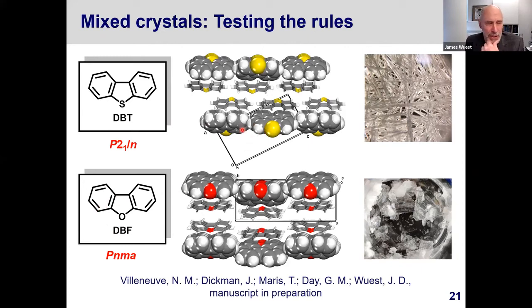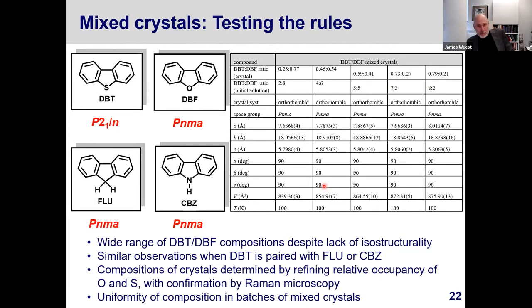The structures are certainly related. I'll show you pictures here. There are herringbone interactions, stacking arrangements. They're not easy to describe, but they're related. The signature of a dibenzothiophene crystal is the formation of an elongated needle, whereas dibenzofuran crystallizes in flat plates. So when you crystallize compounds of this type, you know what you're getting just by visual inspection, but I'll have more to say about that later. It also turns out that fluorene and carbazole crystallize like dibenzofuran in the Pnma structure.